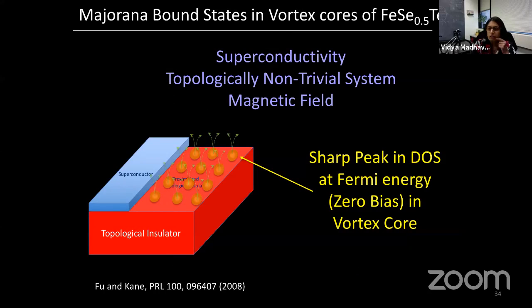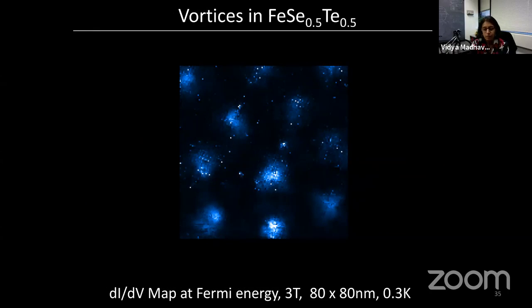Now what do you expect when you turn on a magnetic field? Like I said, in such a system, which is a topologically non-trivial proximatized system, if you turn on a magnetic field, in the vortex cores you should see a sharp peak right at the Fermi energy. This would be your Majorana bound state. Here's a map of the vortices when you turn on a magnetic field. This is almost hexagonal. It's not perfect, but it's almost hexagonal. These dots that you see are actually not noise.